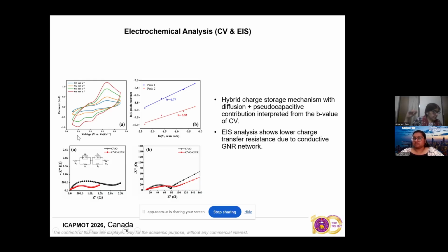And recent studies have revealed that the two redox peaks in CV can be attributed to the sequential intercalation of zinc ions in two distinct crystallographic sites. Now, one can also see that the CV curves of the CVO GNR cathode at different scan rates retain their fundamental shapes despite subtle shifts in the peak positions.